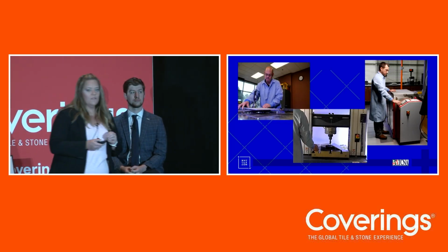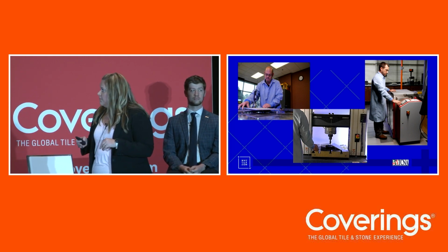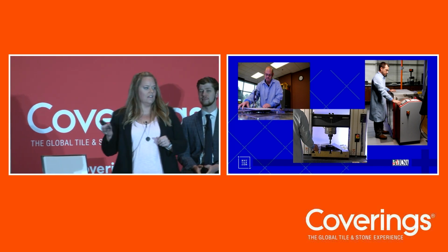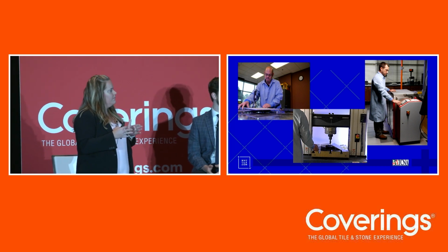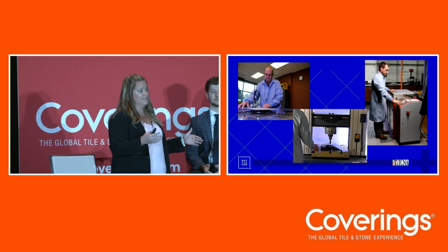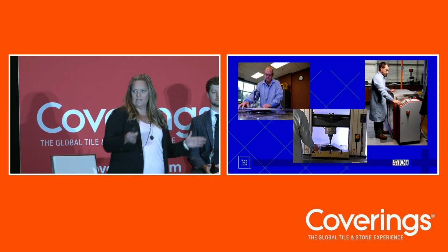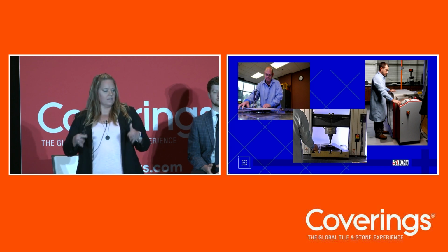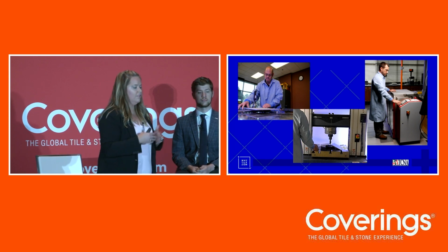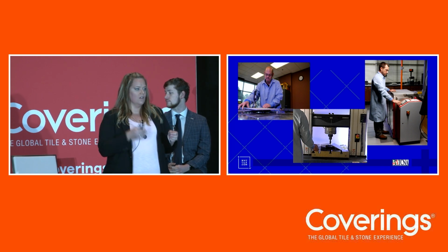So just to show you a few of the tests that we do that are included in the ANSI specifications for tile. In the upper left corner is dimensional testing. One of the important questions we get is, is this tile warped beyond what the standard allows? I'm having problems with installing it without lippage. I don't think that it meets the ASTM standard, or the standard for warpage. So we can make measurements on this table that include facial dimensions, wedging, which is the squareness of the tile, and edge and center warpage as well.